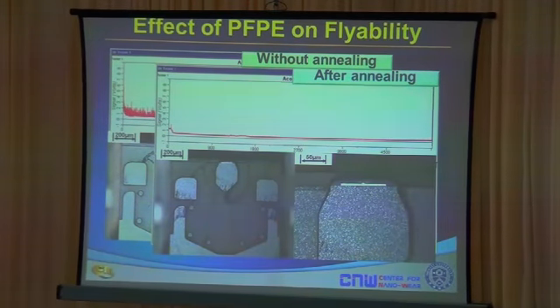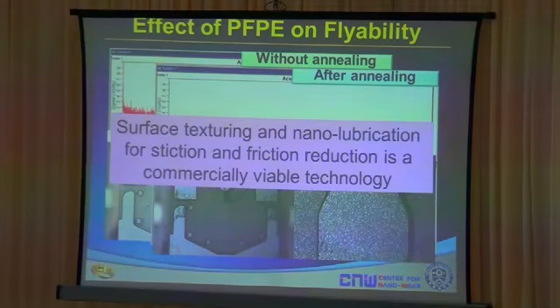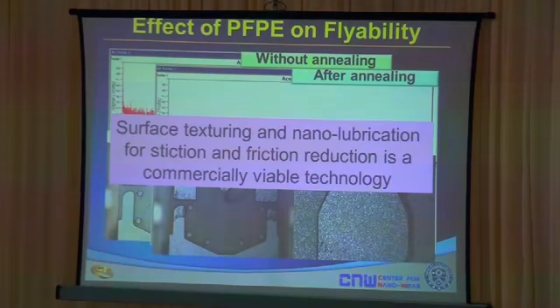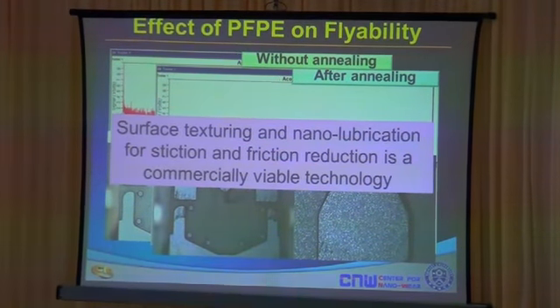If you anneal it properly, you can see that the signal can be controlled to a very stable level. And again, if you look at the transfer of lubricant to the slider, you can see it is significantly less than what you saw before. Therefore, by annealing the lubricant at a proper condition, you can control this problem of friction to a certain level. Therefore, in the case of a very well commercialized product like the hard disk drive, surface texturing and nano lubrication for stiction and friction reduction is a very commercially viable technology.